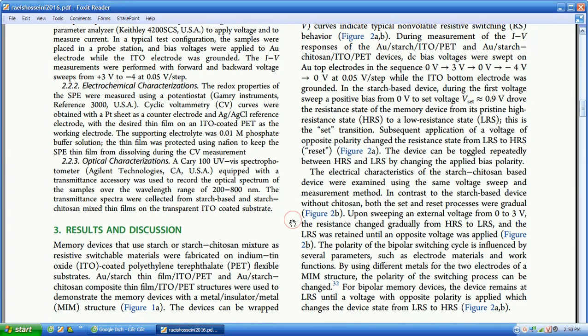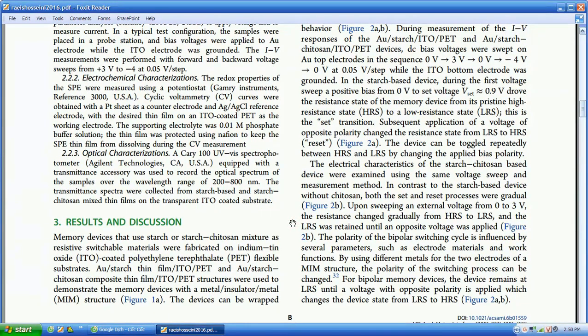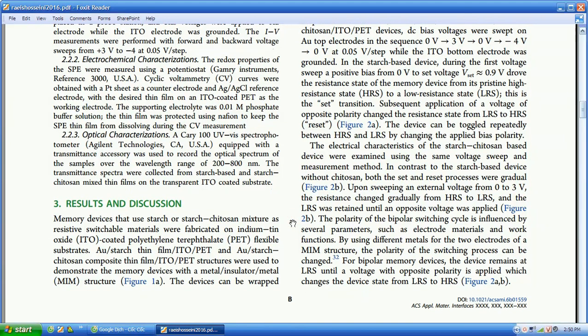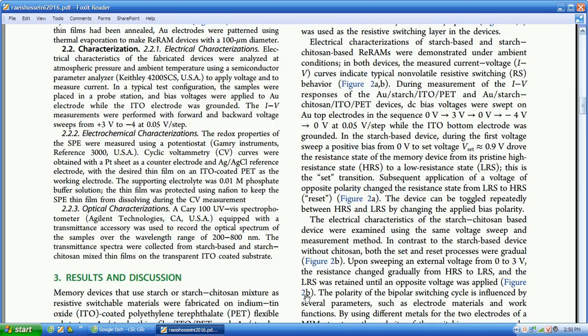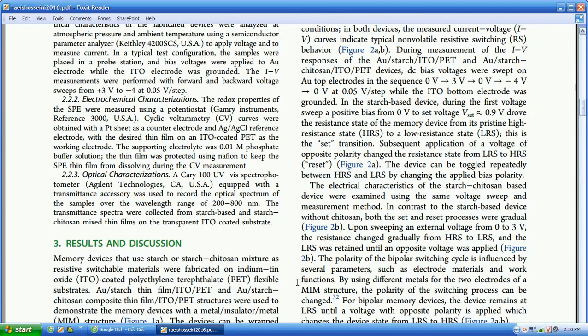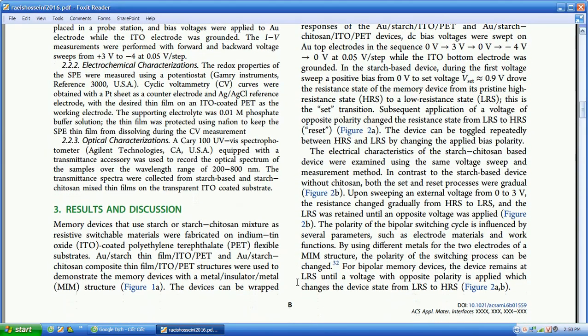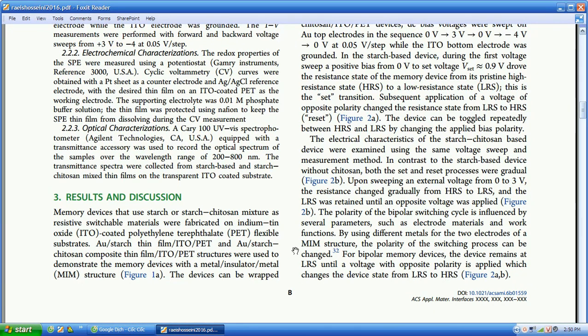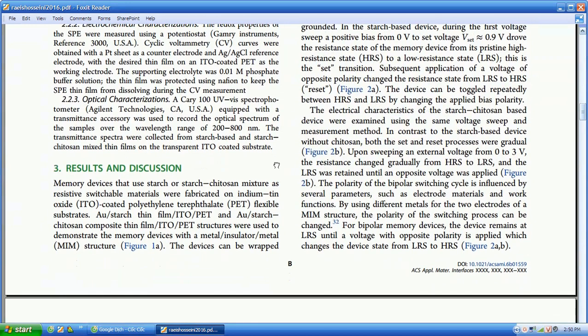In the starch-based device, during the first voltage sweep a positive bias from 0 V to set voltage, V set, approximately 0.9 V drove the resistance state of the memory device from its pristine high resistance state, HRS, to a low resistance state, LRS. This is the set transition. Subsequent application of a voltage of opposite polarity changed the resistance state from LRS to HRS, reset, figure 2a. The device can be toggled repeatedly between HRS and LRS by changing the applied bias polarity. The electrical characteristics of the starch-chitosan-based device were examined using the same voltage sweep and measurement method. In contrast to the starch-based device without chitosan, both the set and reset processes were gradual, figure 2b. Upon sweeping an external voltage from 0 to 3 V, the resistance changed gradually from HRS to LRS, and the LRS was retained until an opposite voltage was applied, figure 2b.